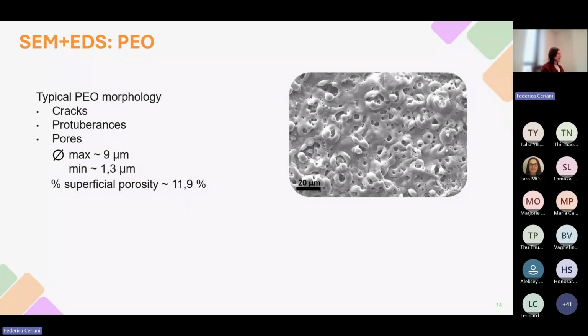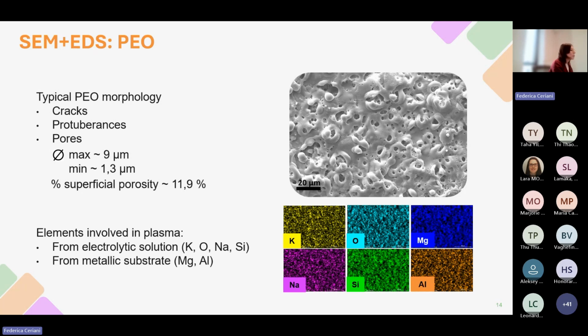By looking at the SEM image, we could observe a morphology that is typical of PEO coatings, characterized by the presence of cracks, protuberances, and pores. Then, according to the results provided by EDS maps, we could note that elements coming from both the electrolytic solution, for example, potassium and silicon, as well as elements coming from the metallic substrate, mainly magnesium and aluminum, are present within the final oxide layer, meaning that all these elements were involved in the plasma discharge during the PEO treatment.